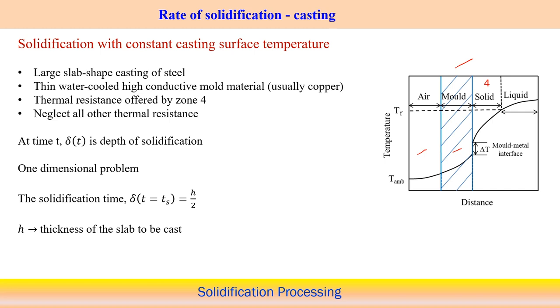Now, suppose that at time t, delta of t is the depth of the solidification. So, we can assume that at a particular time t, the depth of the solidification is delta T, and this is the mold surface, which is very thin as well as water cooled. So, the heat transfer rate is very high through the mold surface, and here the liquid metal is there, but it is the solidified cast metal, and at time t, delta T is formed. Delta T is the thickness, the depth of the solidification. Of course, we consider a one dimensional problem in this case.